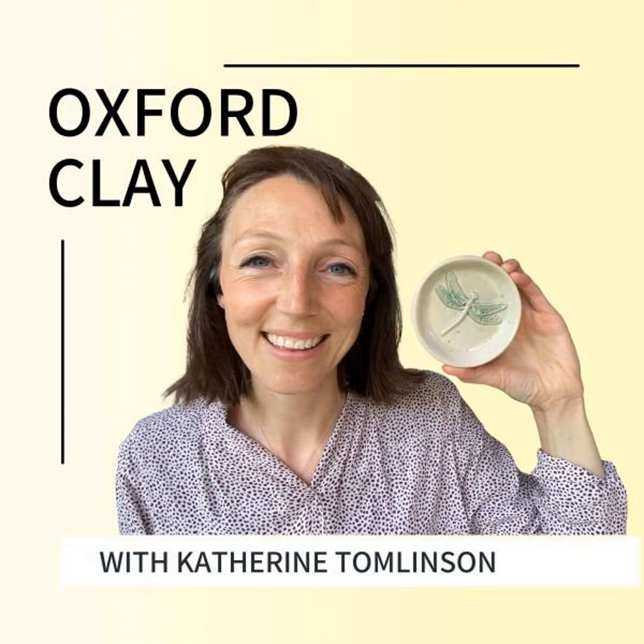So there are plaster sprig molds. You would use slip and score it, and that's how you would stick a sprig onto your pot, and then smooth around the edges to make sure it didn't come off. The two things would have to be the same level of dryness if you're joining them together, so that they didn't crack off. If they're different levels of dryness, then they can crack apart. So when you're joining something decorative onto your pot, you just need to make sure they're the same level of dryness.